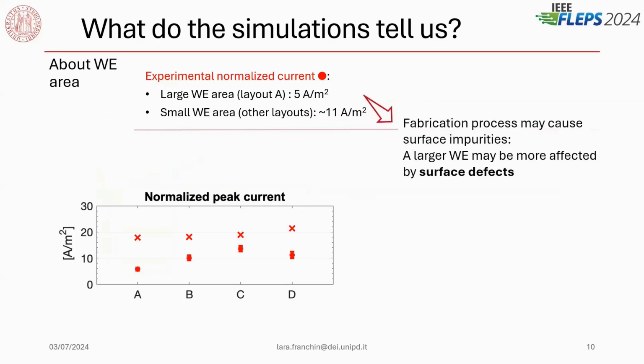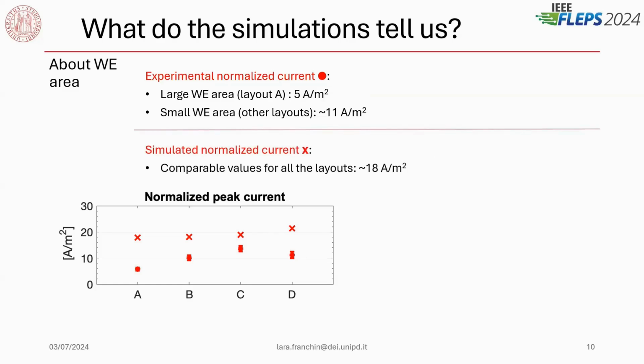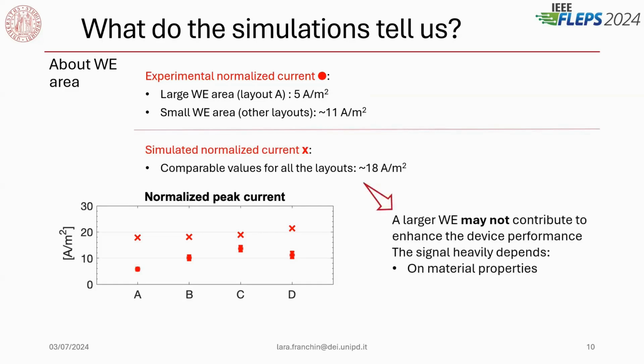And we thought that this was due to the fabrication process. So a large working area may be more affected by impurities, more roughness, defects, and porosity on the electrode. Meanwhile, by taking a look at the simulated currents, we can see that the values are almost comparable for all the layouts, which means that even in theory, a large working electrode may not actually contribute to enhancing the device performance, and this further confirms the fact that the signal is heavily dependent on the material properties.